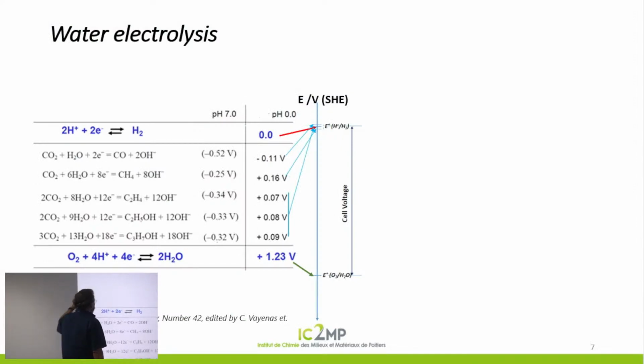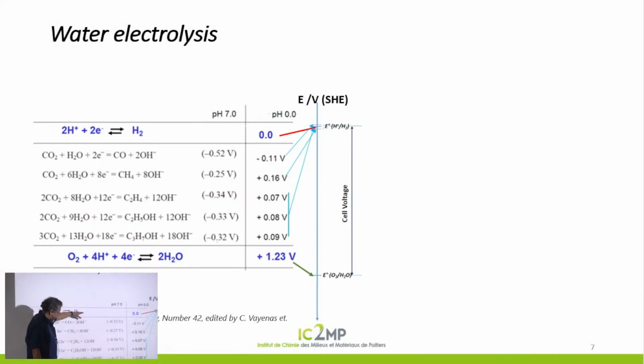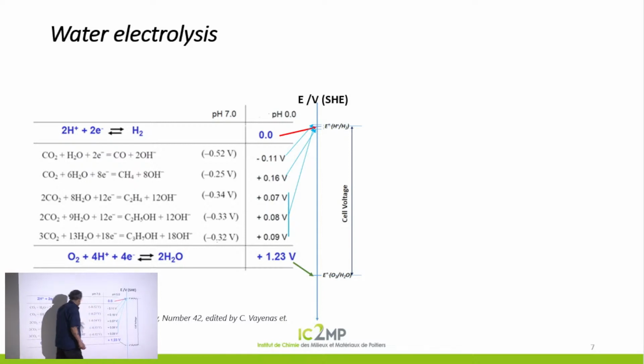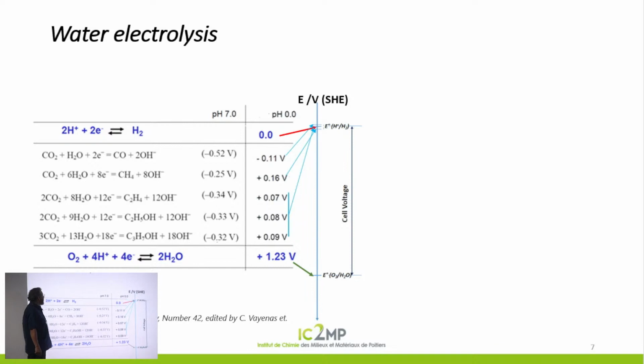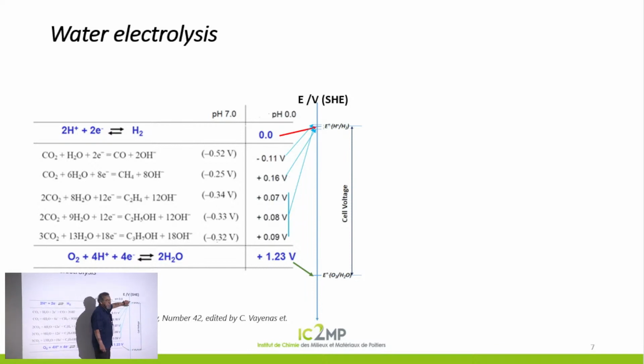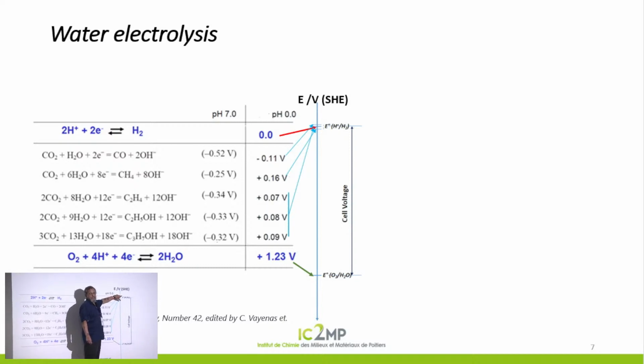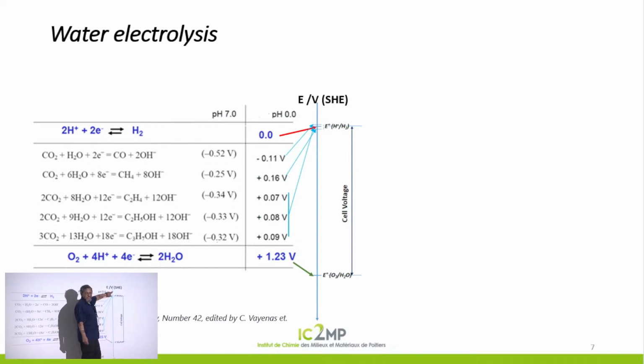Now, with this knowledge we have here the energy for the hydrogen electrode and the energy for the oxygen electrode. In between, I wrote here, because that is also important, to fix CO2. That is also a big challenge in the electrochemical world, how to produce the best catalyst to do this. And you can observe that all these processes, multi-electron charge transfer processes, from 2 to 18 electrons, in order to produce fuel, are all around the potential of the hydrogen electrode. So if I am able to develop a system, I could fix the problem of greenhouse gas, right, by fixing CO2 and evolving oxygen. Or the easiest way is to evolve hydrogen and oxygen, in the case of water splitting.